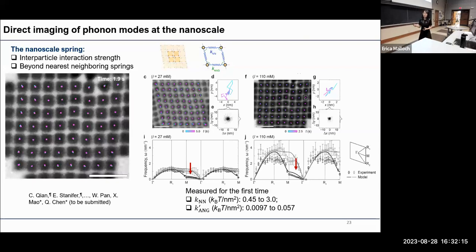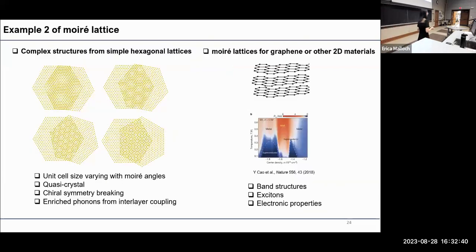So if you pay attention to the values, it turns out the K angular are actually orders of magnitude smaller than the K radial, which really means the system is rotationally really flexible and longitudinally really robust, which is exactly the feature for Maxwell lattice. So this study can show you how to think about how to measure phonon dynamics at nanoscale. And the next example is a little bit exotic.